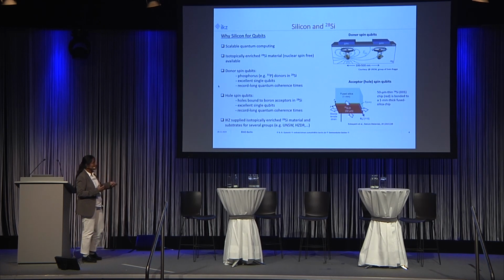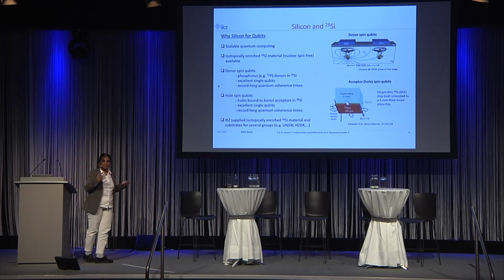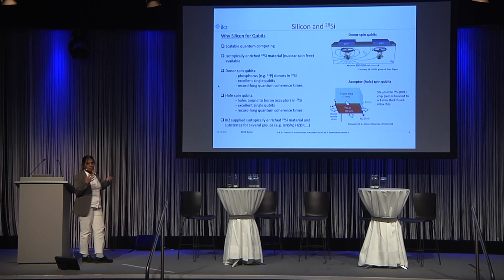This is how the device was fabricated: the boron is doped in isotopically enriched silicon-28, and this was thinned down to a 50 micrometer slice, and this was bonded to fused silica, so that you can create a strain in the layer. The strain is very important to achieve very high mobility in the devices. I would like to point out here that our institute has supplied this isotopically enriched material in the form of substrates, and also in the form of targets for MBE layers, to grow the MBE layers for several groups worldwide.